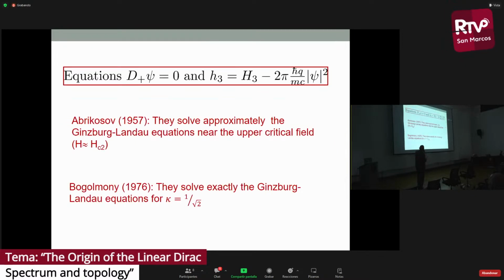So these equations solve approximately the Ginzburg-Landau equations near the upper critical field. That's what Abrikosov solved. And what Bogomolny found in the 70s is that they solve exactly the Ginzburg-Landau equations for kappa equal to 1 over square root of 2.